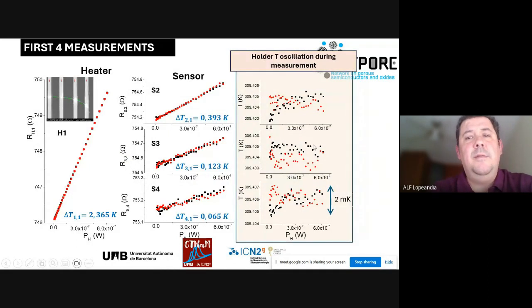If we do the first measurement, just heating up the first nanowire, we heat it up introducing very little power. It's around 10 to the minus 7, that is 600 nanowatts.